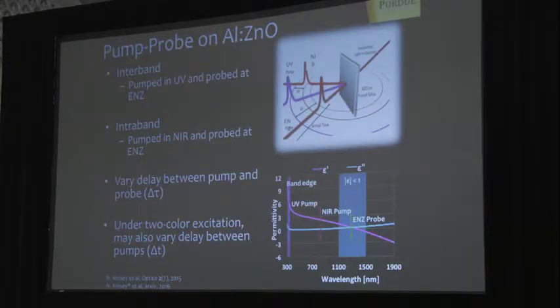So it works in a different direction, this nonlinear response. And it turns out to be also very fast, also on the scale of 100 femtoseconds, which is indeed very important. It opens up the possibility to really control nonlinear response in a very interesting way if you could send, let's say, two different pumps. One is UV, which would enable this interband transition. Another is near-infrared, 800 or so, which would enable this intraband nonlinear response. And by controlling the delay between these two pumps, we actually could control the nonlinear response. And of course, you also could control the delay between the probe and these two pumps.